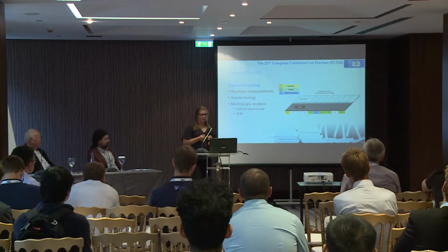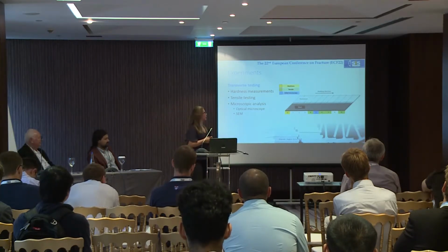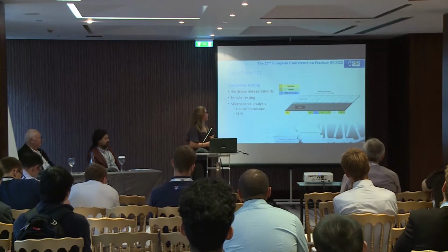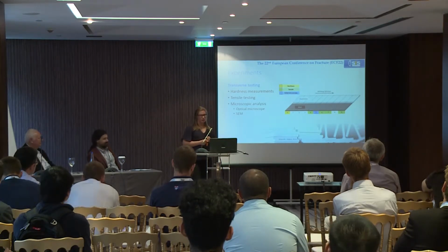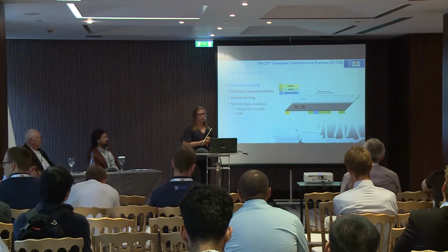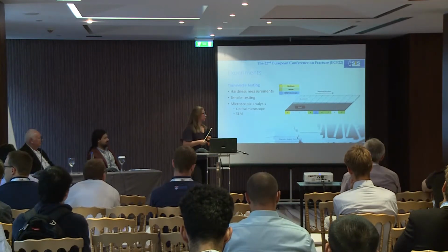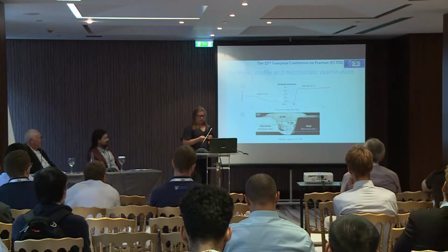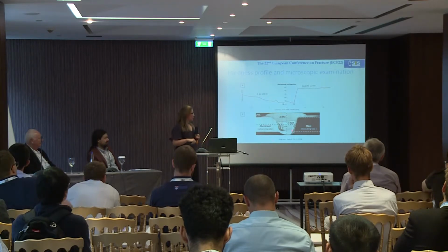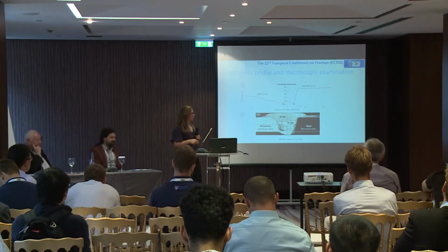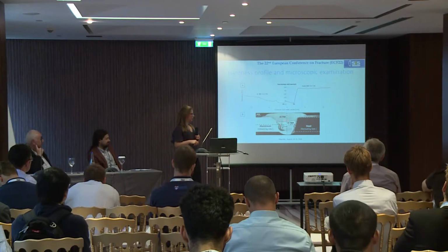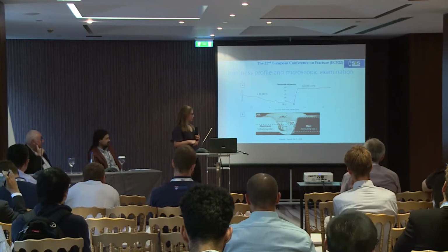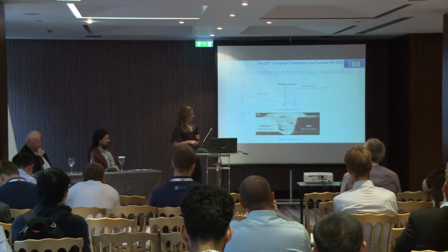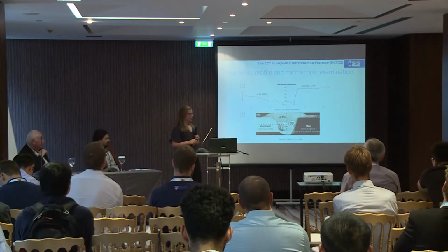So the experiments we have done are transverse testing, like hardness measurements, tensile testing and microscopic analysis, including both optical microscopy and SEM. So here you can see the hardness results and an optical micrograph of the joint. And here you can clearly see the aluminum filler wire. This is the dark part. And the aluminum base material. And you can also see that the steel is not deformed at all.